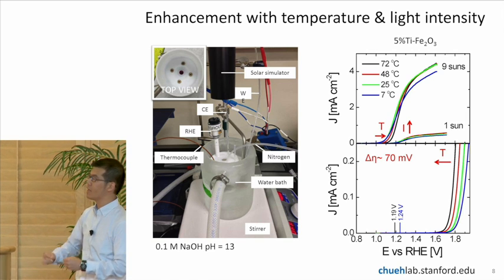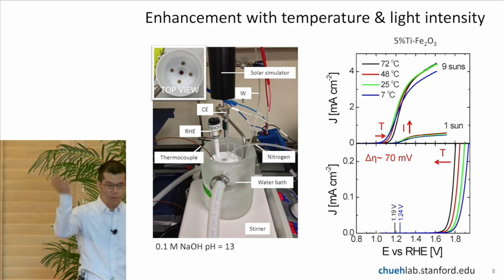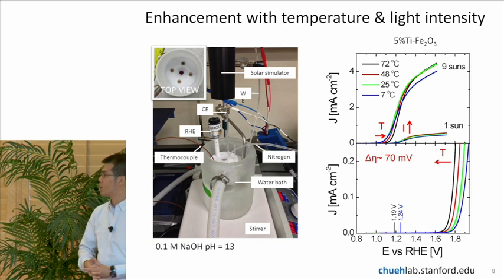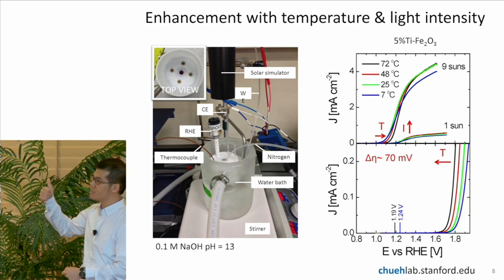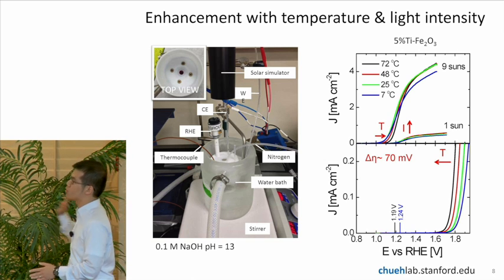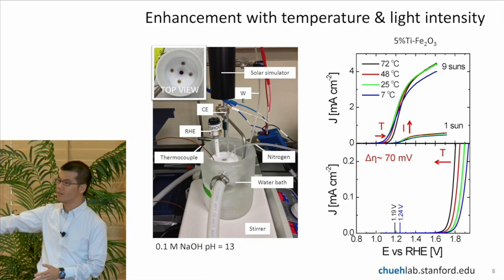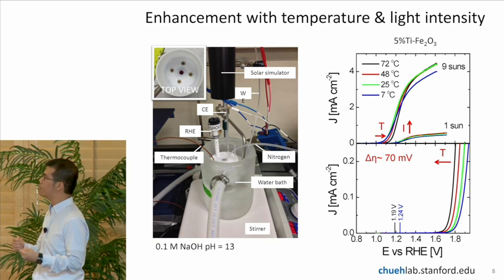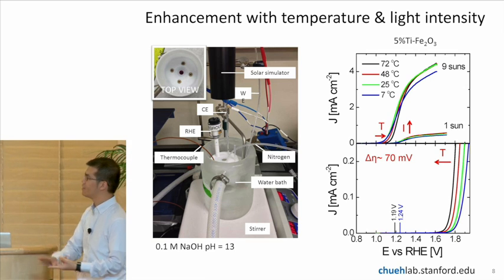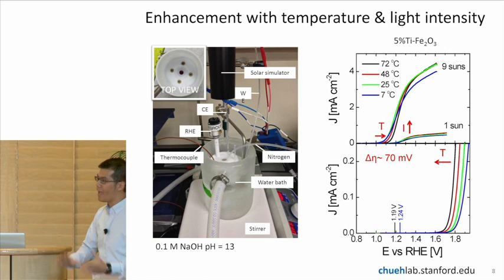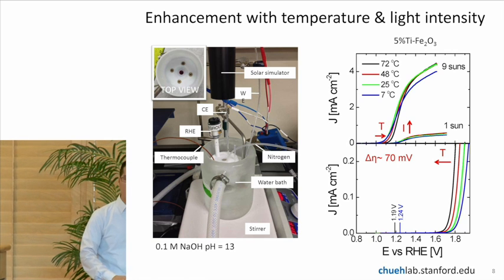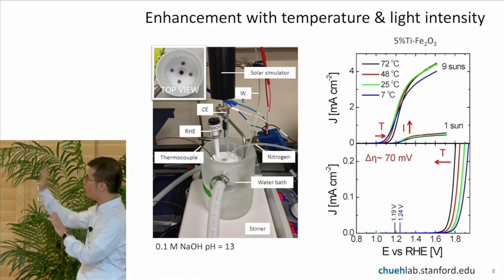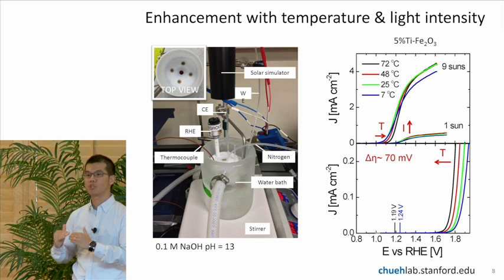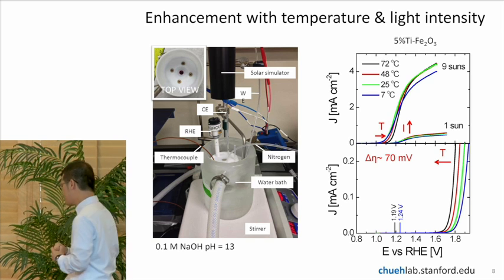And then furthermore, if we concentrate the light, we're able to substantially increase the current. And also by increasing the intensity of the light, you're also shifting the voltage to the left as well. So by carefully playing with temperature and light intensity, we're able to do what we want, which is push the voltage to a lower value on this plot and push the current higher.